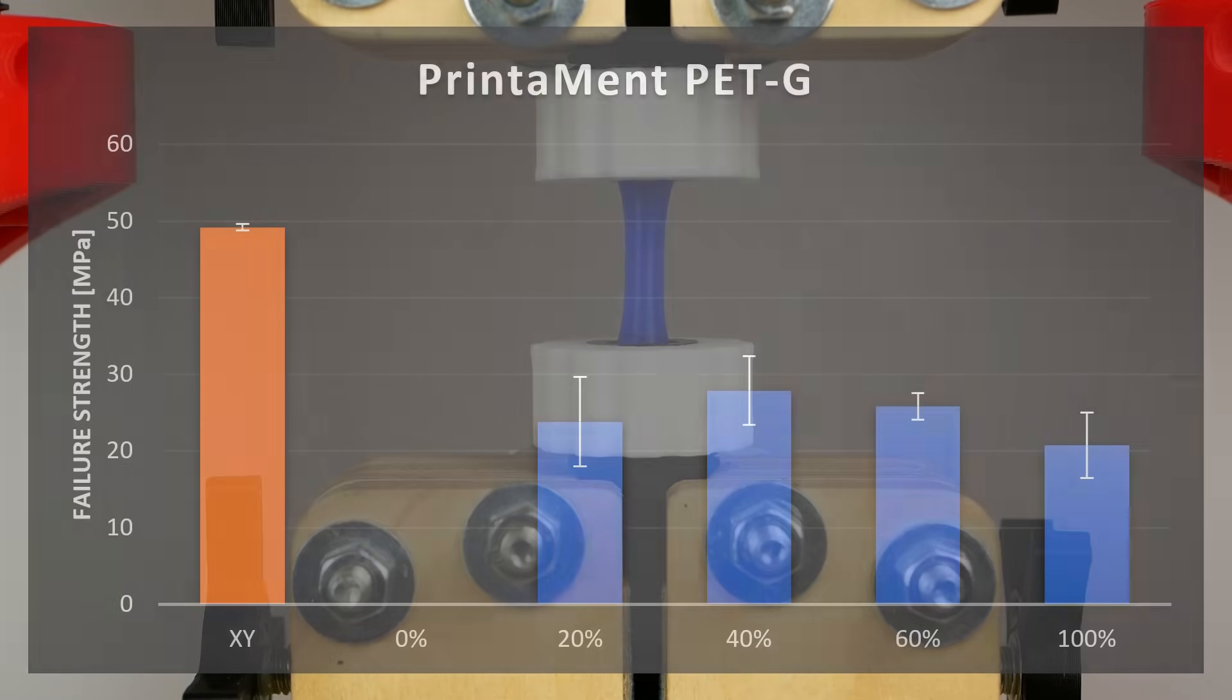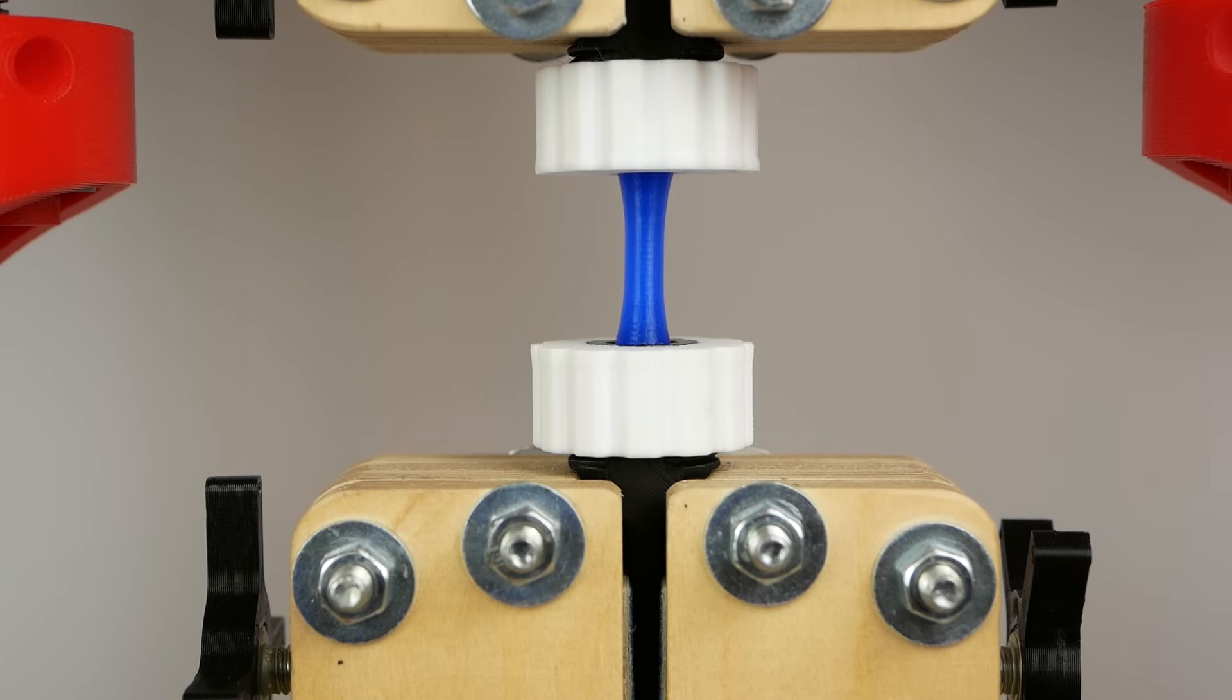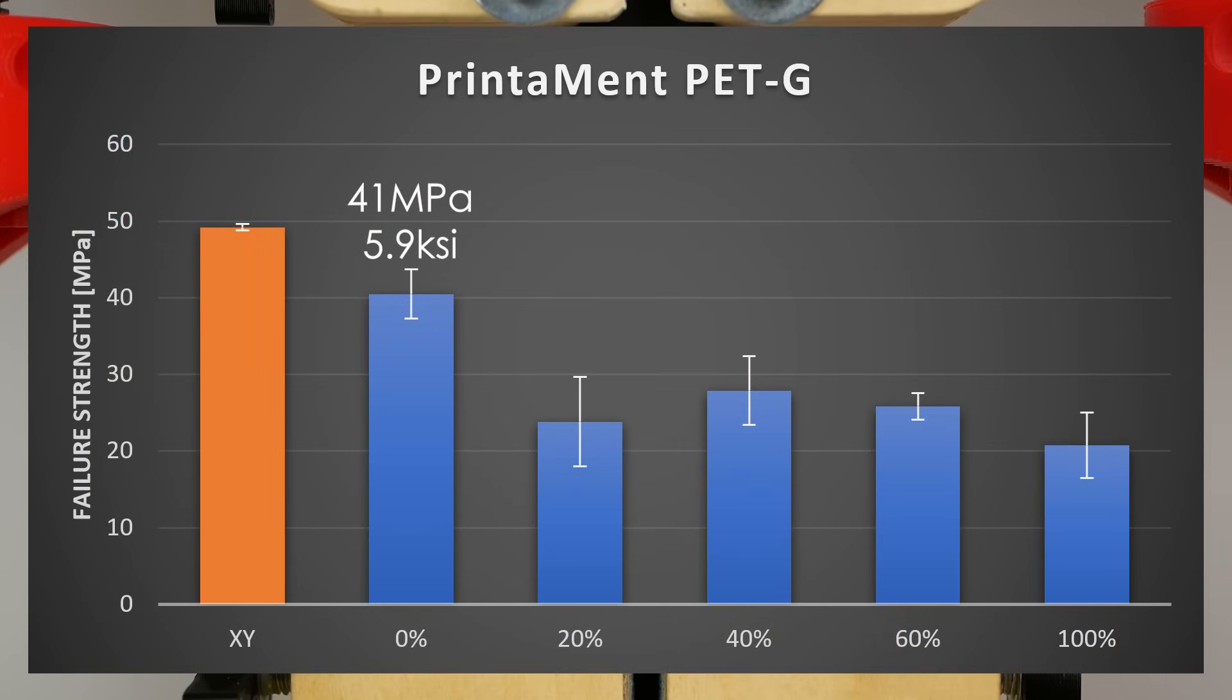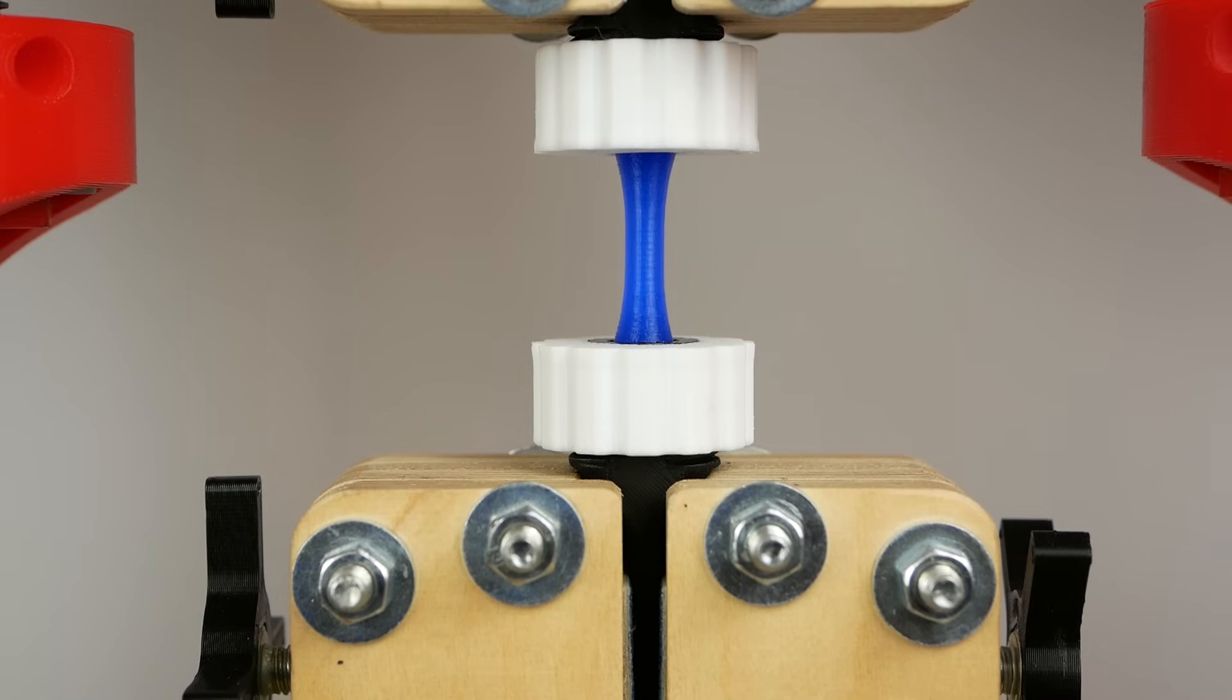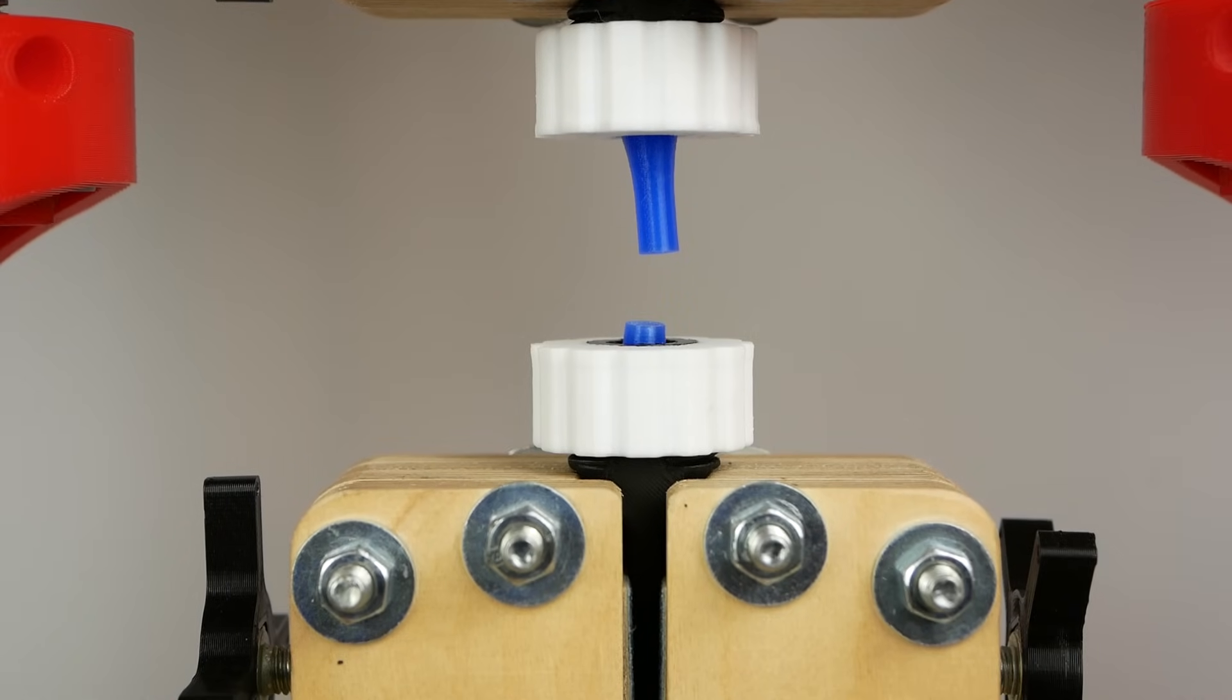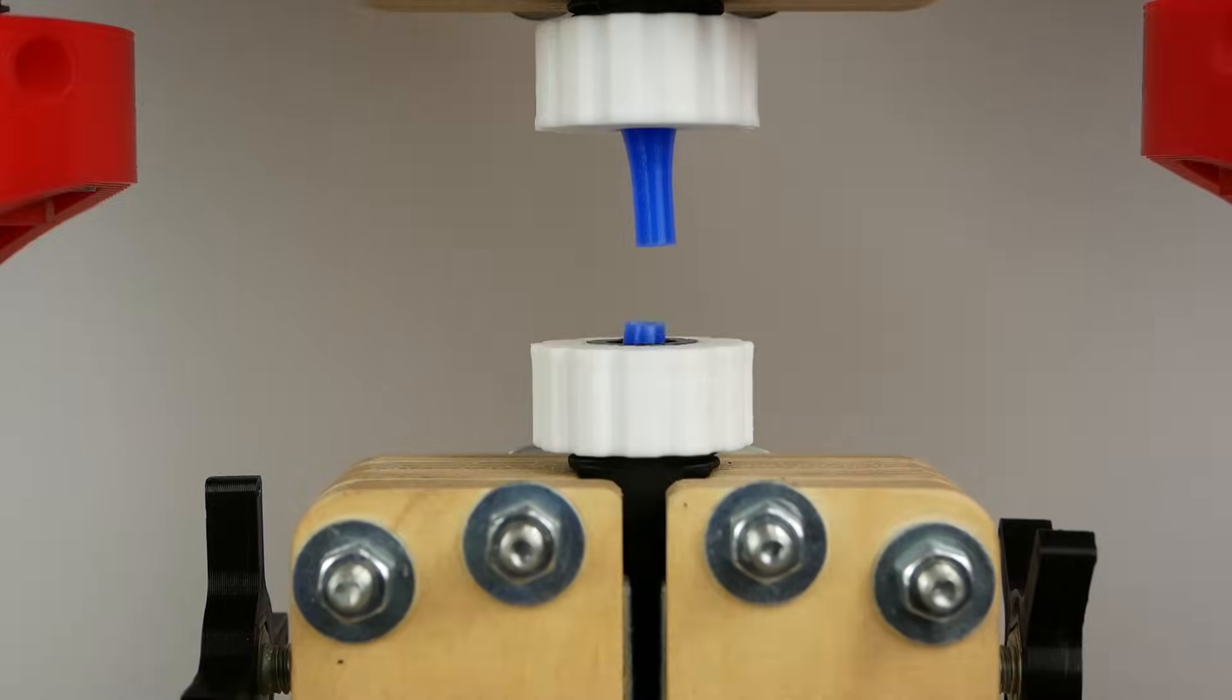Only the samples printed with no fan at all were able to bear almost 41MPa before they failed which is only less than 20% lower than our baseline and therefore very impressive. The results kind of confirm what my suspicions were in the past. PETG still seems to be a bit more tricky to print and therefore the results scatter more.